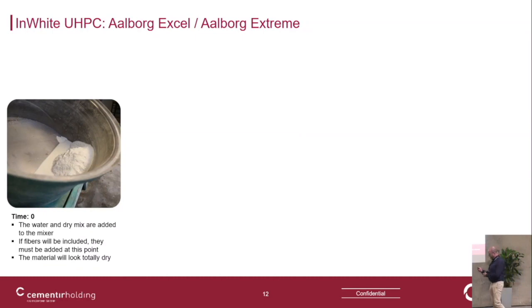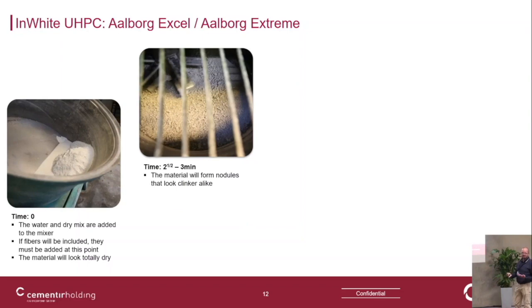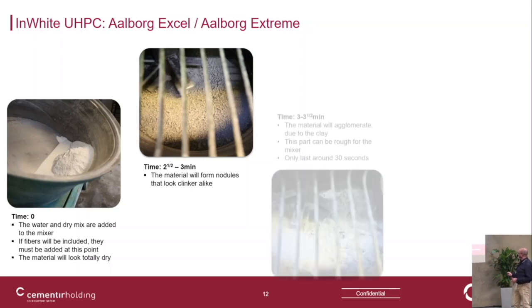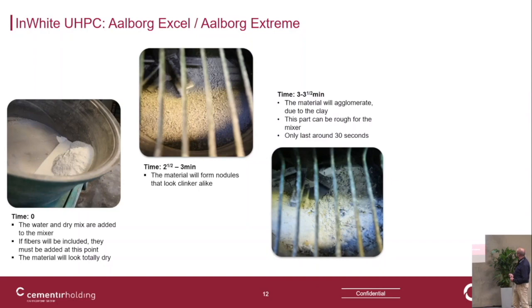To give you an idea of the mixing instructions, it is a special premix where the superplasticizer is included. After adding water, in the beginning you can also add pigments if you want, but it takes a lot of time and a lot of energy to reach the good consistency. After 2-3 minutes, it's a bit strange. It's a very dry mix forming little nodules. And after some more time, the small nodules become bigger, and then you come into the phase we call the clay phase.